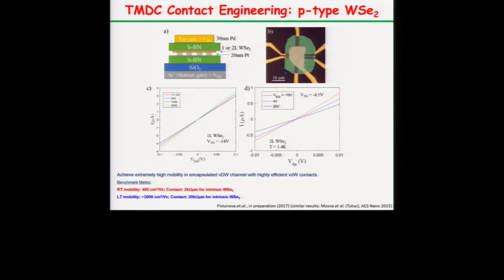What we have to do is also, if you notice here, there is a top gate. This top gate is in charge of doping the contact area as well. So it dopes the contact, and it can also control the channel doping. But we also have a bottom gate. The bottom gate can take care of charging the channel itself, but the top gate is very useful to dope these contact areas.